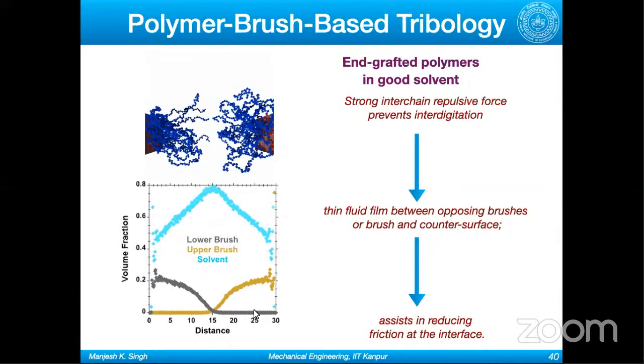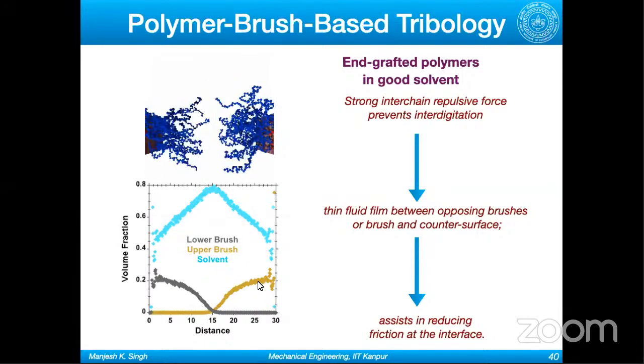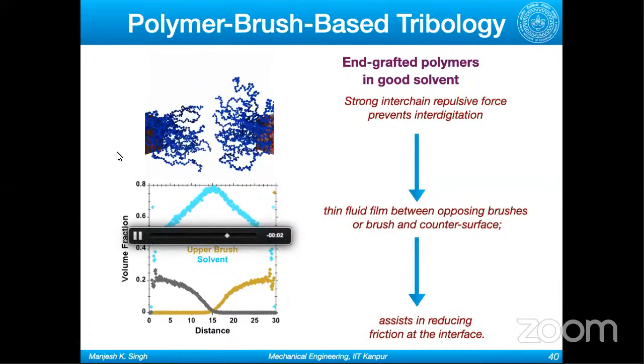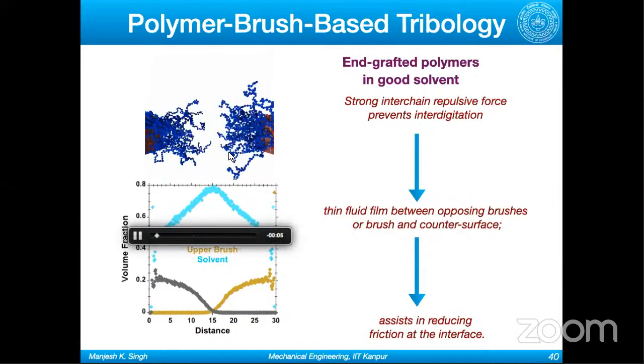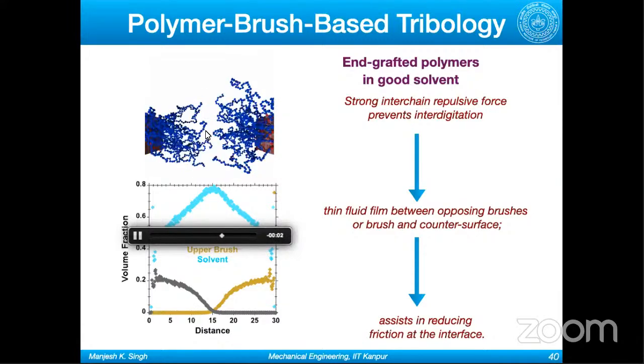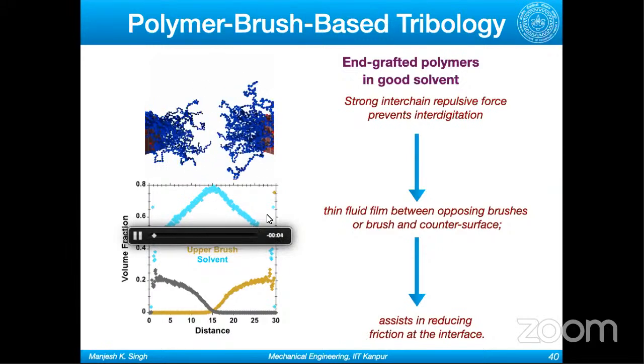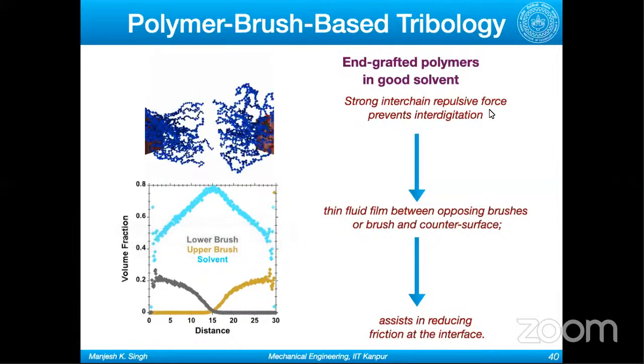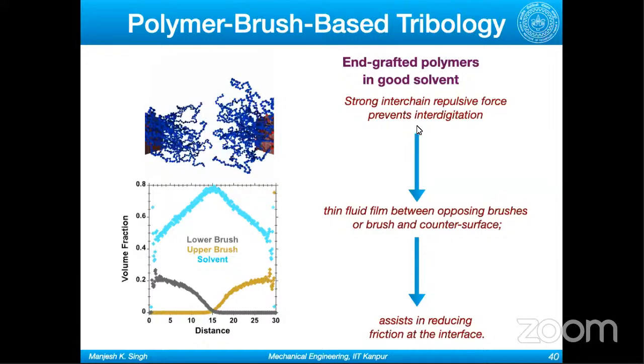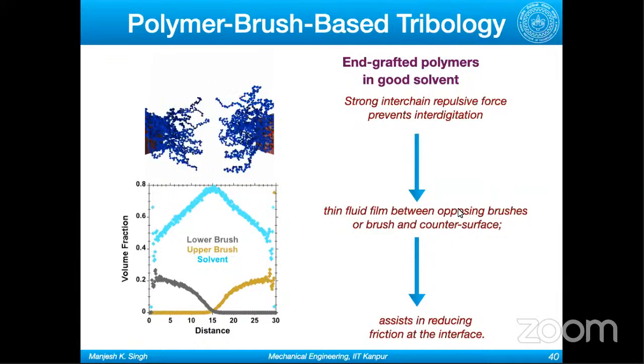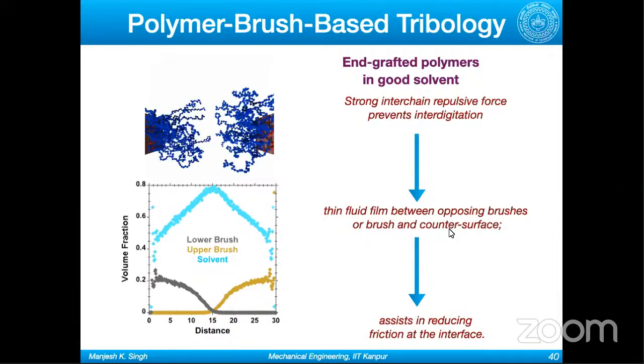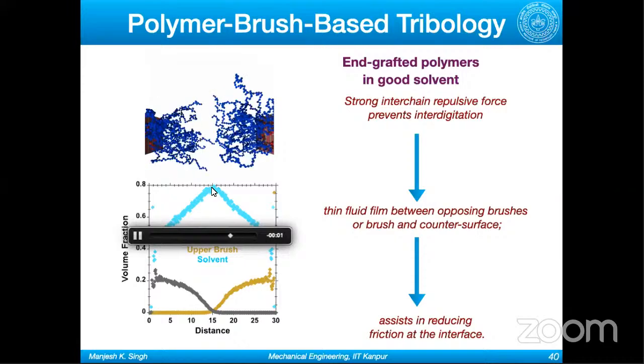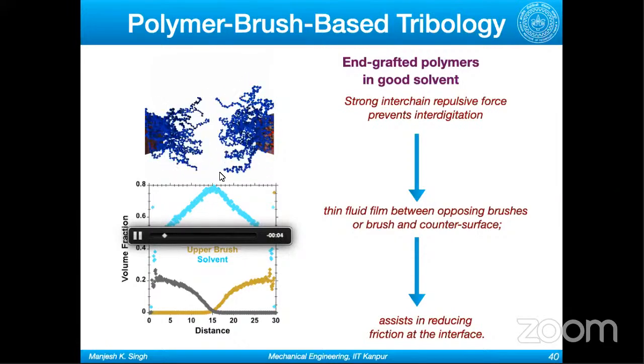that the gray and yellow curves are for the polymer or monomer density. As you move away from the grafting surface, their density is going down. But at the same time, if you look at the solvent particle density, which is not shown here in the snapshot or in the animation, their density goes up. So what exactly happens is that polymer brushes, because of strong interchain repulsive force, prevent interdigitation, and the thin fluid film supports the normal load between opposing brushes or brush and counter surface. So there's this thin film of fluid or liquid in between, which takes care of lubrication, or assists in reducing the friction at the interface.